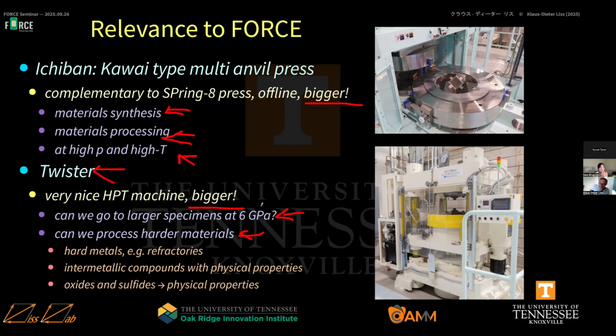Yeah, thank you so much for the question. The grain size. So what typically people do is you can determine the grain size or the coherent diffraction volume size, that means between the dislocations, with the Williamson-Hall plot. And there you can go into maybe, if you do it very well, the 100 nanometer range. It's more suitable for the 10 nanometer range. With the microbeam diffraction, by counting the reflections on the Debye rings and working out how many grains are in the illuminated volume, which we know, we also can estimate the grain size.